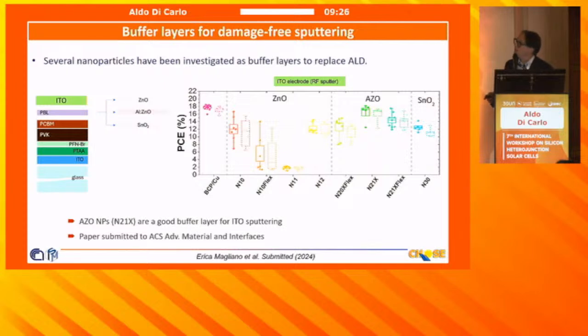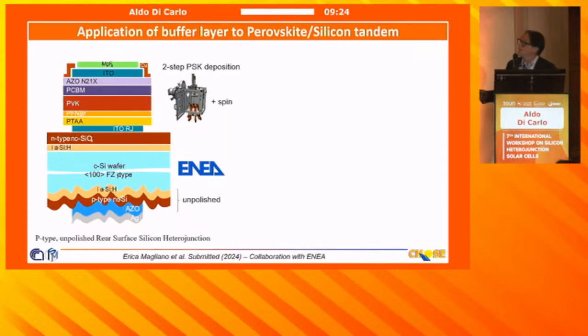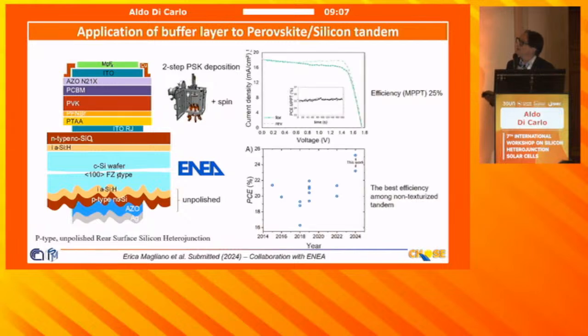So in this way, together with Enea, that was providing the bottom cell, which is polished on one side and not polished on the other side, we were doing the full tandem by using AZO nanoparticle instead of ALD tin oxide, and the efficiency we got was 25% at MPPT, which is one of the best for the polished silicon tandem with perovskite. Okay, so this is a way to do it.